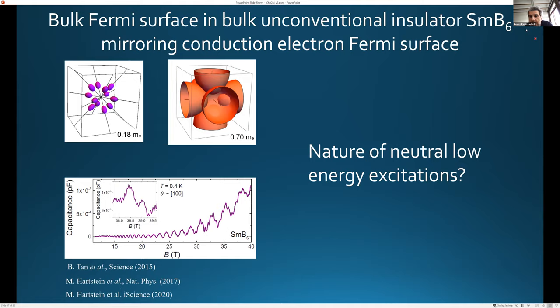It seems that there have been several occasions where, in different materials, oscillations are either seen in the resistance and not seen in the magnetic moment oscillations, or the other way around. And could you gauge your story with respect to these occasions? Oh, right. So I guess there's a few reasons why that might happen. Different techniques are sensitive to different parts of the Fermi surface. So I think most of the cases you talk about are probably in metals, because until this finding, all quantum oscillations were reported in bulk metals, bulk semiconductors, et cetera.